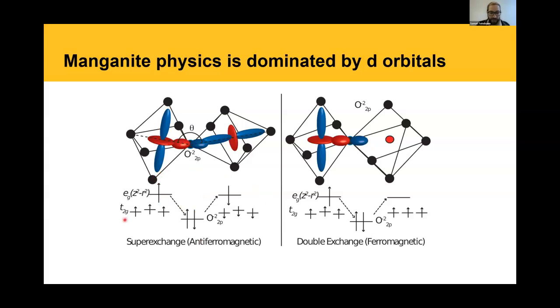if you have, let's say, a lot of d orbitals everywhere, you would not favor hopping interactions because you want this manganese site to be all spin up and this manganese site to be all spin down so that you can hybridize this d orbital with this d orbital through the p orbital. This is known as the super exchange interaction. On the other hand, if you have an empty d orbital, then you would like all the spins to align to favor Hund's rules. And so if you have a system with manganese 3 and manganese 4 ions, you can have both antiferromagnetic and ferromagnetic favoring interactions in the same system.